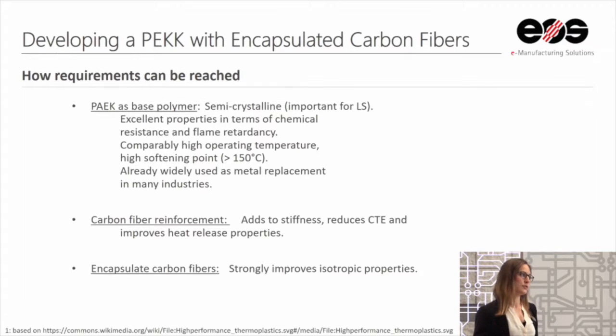And we decided to encapsulate those carbon fibers. By encapsulation I mean they are really encapsulated in the polymer particles that we put in the machine. So another alternative would be you just take the polymer powder, you take the carbon fibers, you mix it, dry blend, and you put it in the machine. But what we did is we compounded it into the polymer particles, and you're going to see why that was our approach and what the outcome is.